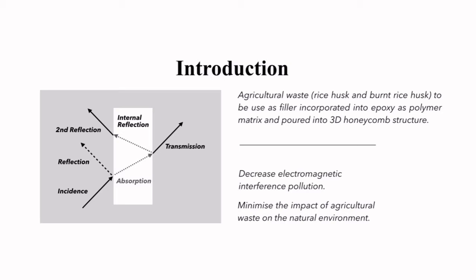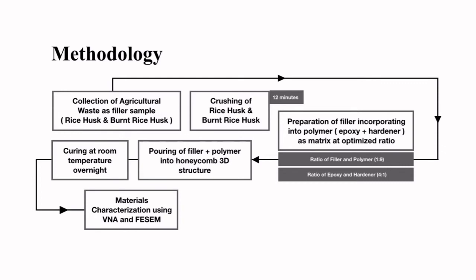These electromagnetic absorbers are able to decrease the EMI pollution while minimizing the impact of agricultural waste on the natural environment. For the methodology, firstly we collect the rice husk and burnt rice husk commercially. Then we powdered them using a crushing machine for up to 12 minutes each in order to get a fine powder size. Then the powder is incorporated into a polymer matrix.